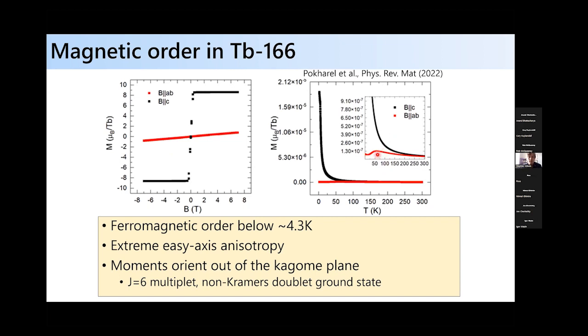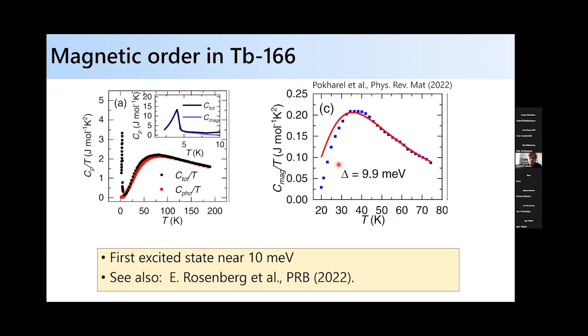You can look at it a bit more in detail if you look at the heat capacity and fit it to a two-level Schottky anomaly. And so basically the first excited state is around 10 millielectronvolts. And you can also use the heat capacity to see the onset of ferromagnetic order at about 4.3 Kelvin. So, okay, the picture for the terbium vanadium 6 tin 6 system is that you can take this Kagome band structure and interface it with a c-axis aligned ferromagnetic state with a strong uniaxial anisotropy.